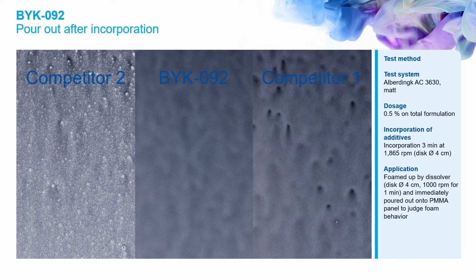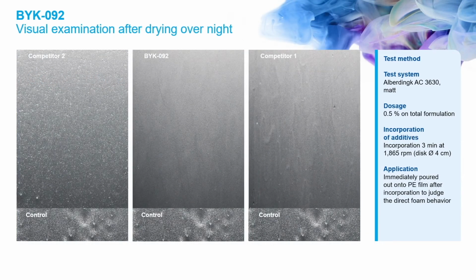Then we take the same PMMA plate, let it dry for about 12 hours, and afterwards we do the visual examination again. So on the left-hand side, you can see the foam is really incorporated into the surface during the drying process, so no air can leave the system.